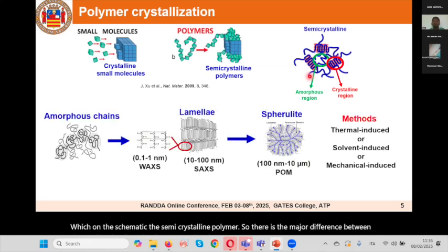Okay, coming to the next one, the crystallization process in the polymer material. The crystallization starts from the random system, that is the amorphous polymer. To these amorphous polymers, by giving some external force, whether thermal, solvent-induced or mechanical force, these energies induce chain mobility. This chain mobility slowly induces crystallization that forms a smaller crystallite. This smaller crystallite eventually acts as a nucleation for further growth into a bigger structure, called lamellae. These lamellae further grow into a macro structure called spherulite.